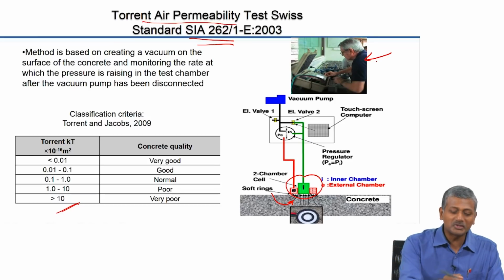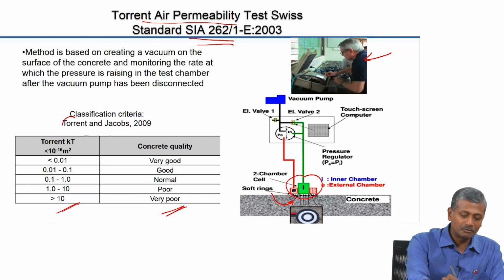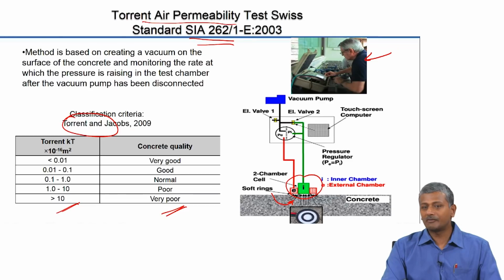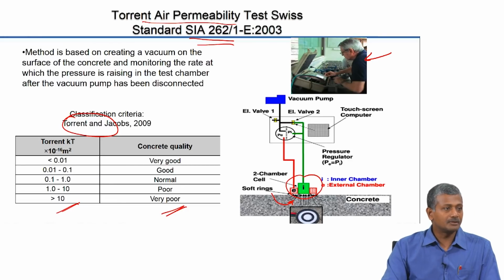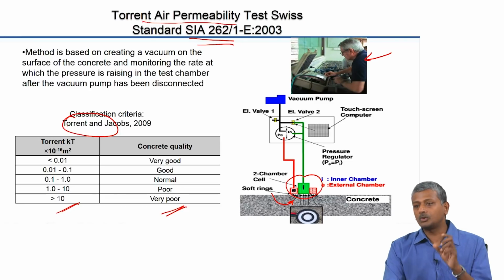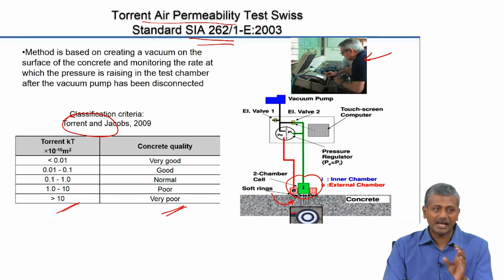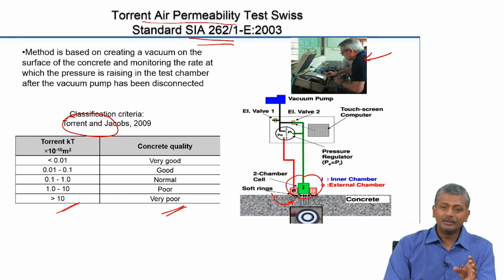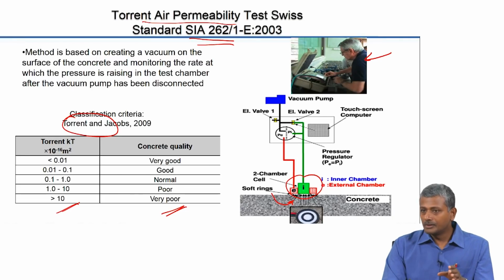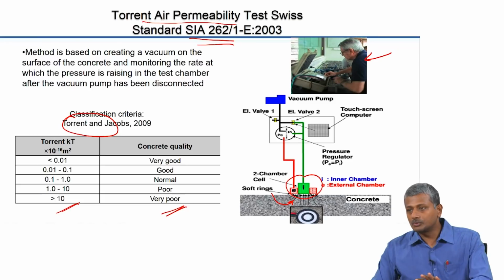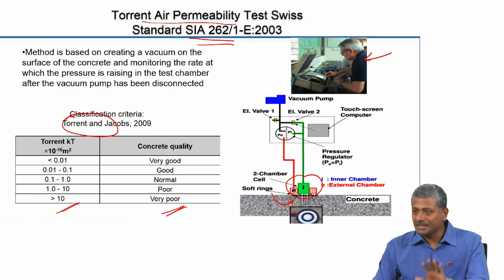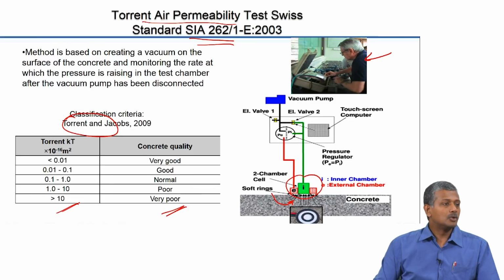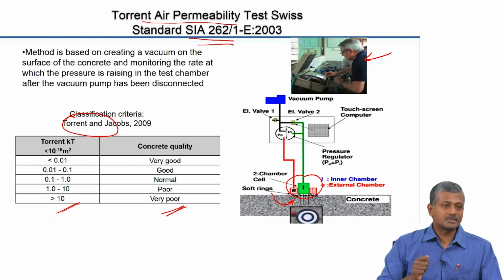Okay. So, based on this again, you can have, of course, from a publication from the manufacturer himself, there is actually a classification for concrete quality that can be done based on the permeability coefficient in the Torrent Air Permeability Test. Now, in this case, what you need to ensure is the concrete is dry. We are talking about gas permeability. So, concrete has to be sufficiently dry. So, although this instrument can be used to calculate the air permeability coefficient of any real structural concrete, you have to ascertain that the concrete in the structure is in a dry condition.